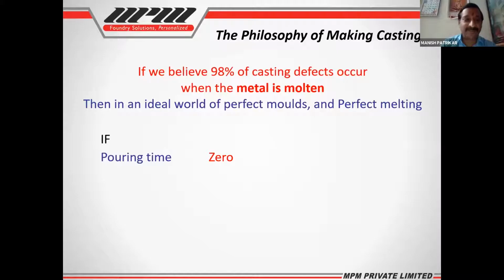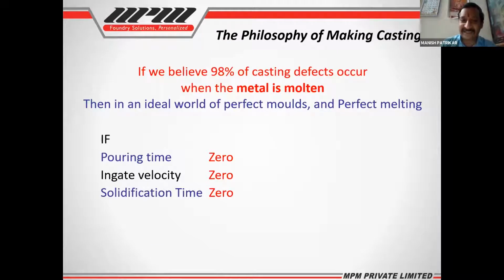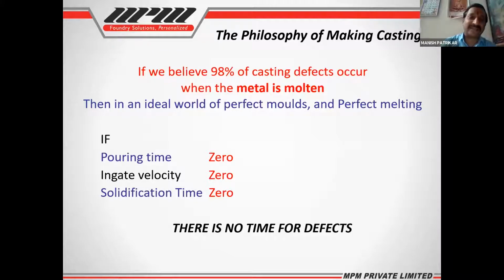pouring time is 0, if ingate velocity is 0, if solidification time is 0, then there is no time for defects. This is the philosophy of making the casting, which is what Sandeep was trying to say in very normal words. I have said this from the metallurgical point of view in technical words. You can imagine if pouring time is 0, ingate velocity is 0, solidification time is 0, there is no time for defects.